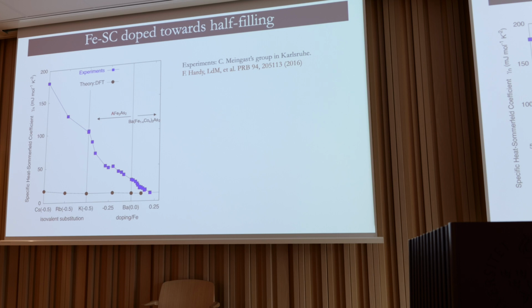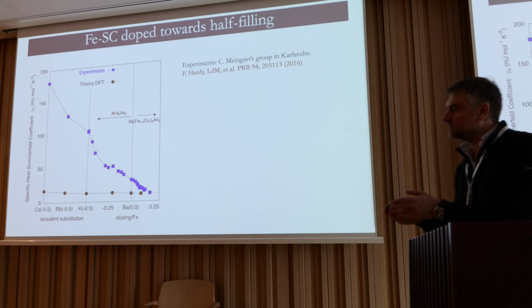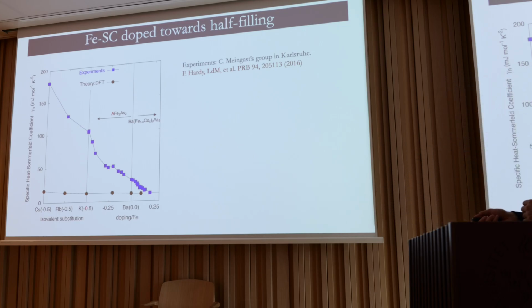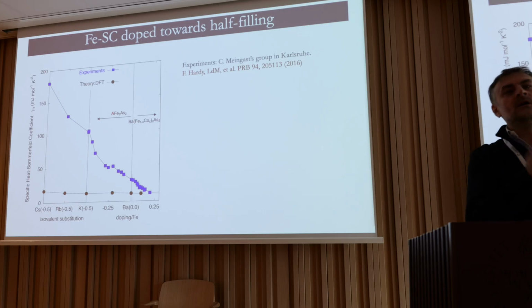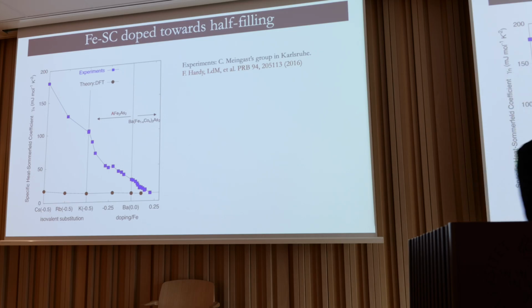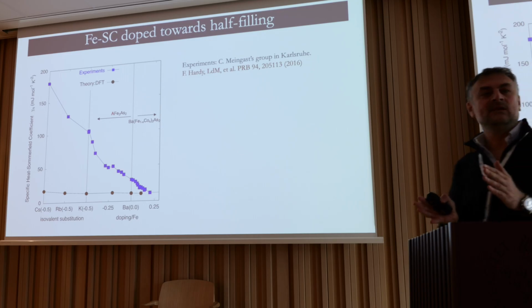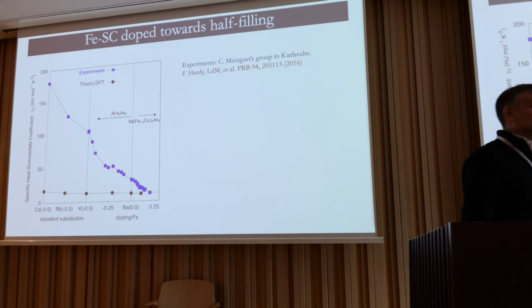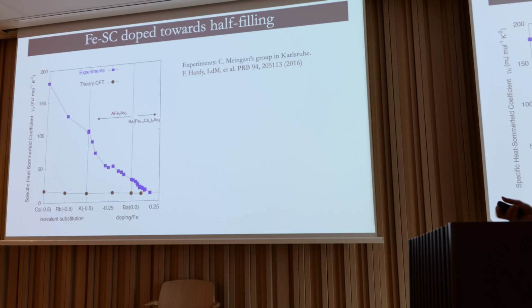So the key point I'm trying to highlight is that the stoichiometric compound barium 1-2-2 has 6 electrons in 5 orbitals, and by the time you've got to potassium, rubidium, and cesium, you have put a hole per iron in the plane. So you're at 5.5 electrons in 5 orbitals - almost at half filling. Half filling would be 5 electrons in 5 orbitals. So you have to weigh towards half filling, and you've got these correlations to go up and up and up.